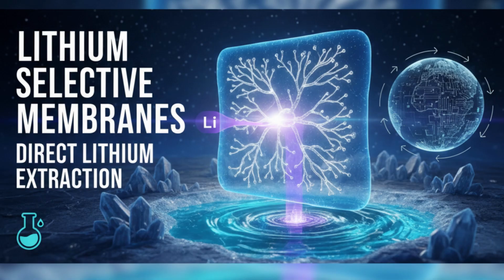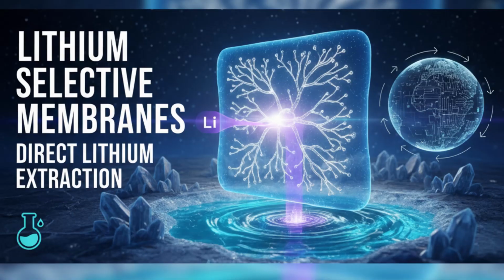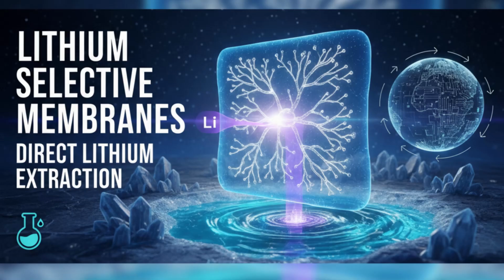It really comes down to subtle differences at the nanoscale and how ions behave in water. There are two main approaches, two mechanisms for DLE, that's direct lithium extraction. The first is what we call the size sieving effect. Now, intuitively, you'd think lithium, Li+, should be easy. It has the smallest bare ionic radius, only 0.6 angstroms. So just make a filter with tiny holes, smaller than anything else, like a molecular sieve.